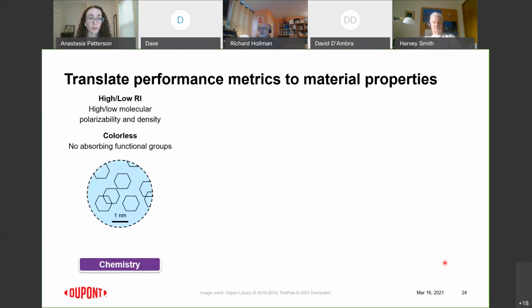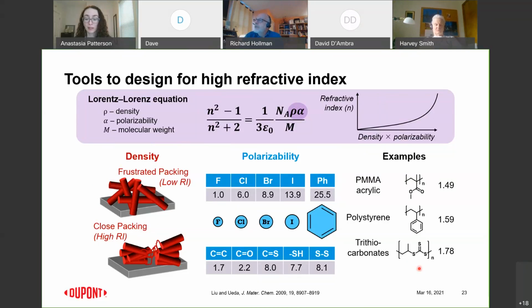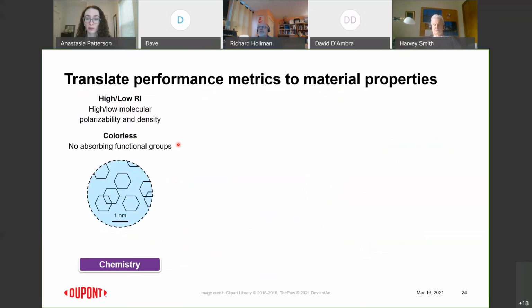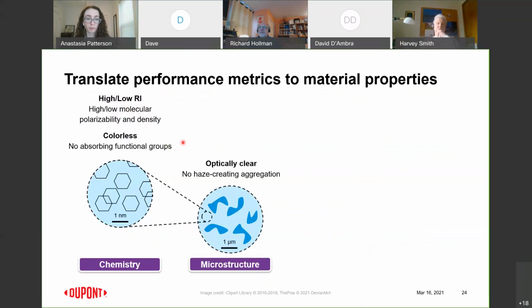So as I mentioned, everything we do is in contact with a customer who has performance metrics that are relevant for getting new devices realized. So I just mentioned some performance metrics we need to keep in mind are, of course, the refractive index target, which we have polarizability and density handles for. But in choosing those functional groups, we have to keep in mind that they can't be absorbing in the visible spectrum. If we used this very highly sulfur-containing molecule for our film, this actually has a red color, and so all of your photos would look like they had a red filter on them if we put that in the path of light. So we already have something that could be in opposition here: colorlessness and refractive index in terms of the chemistry choice.